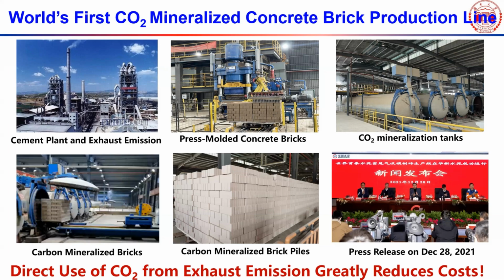And the other amazing thing here is that we use cement flue gas, not pure CO2. Because when you capture and purify CO2, it costs about 6 or 800 RMB per ton. Here, it can actually also purify the flue gas, though we haven't measured it. You can see we do not use any pressure; the flue gas just flows through the many bricks stockpiled inside. Definitely, some particles hitting the bricks will precipitate, right? That's the basic physics.